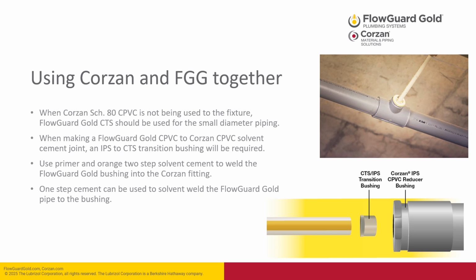In hotels, apartment buildings, and other larger residential type buildings, it is not uncommon to use Corzan and FlowGuard Gold together to make a complete system. If you are using a copper tube size system in conjunction with Corzan Schedule 80 CPVC, FlowGuard Gold should be the pipe used for small diameter to ensure that you're getting the same high quality performance of Lubrizol CPVC at all diameters. When joining FlowGuard Gold CPVC to Corzan CPVC using a solvent welded joint, an IPS to CTS transition bushing will be required.